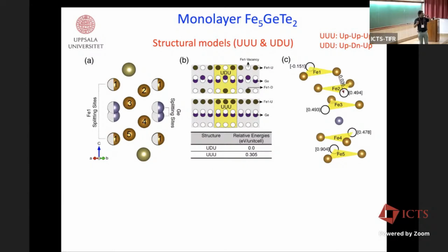And why should we bother about that? We have to bother about that because there is a strong consequence of this structural arrangement on the magnetic properties. If you take these two structural models and do simple-minded DFT calculations, you will see that the UDU has a little bit lower energy compared to the UUU structure, around 0.3 electron volts per unit cell.